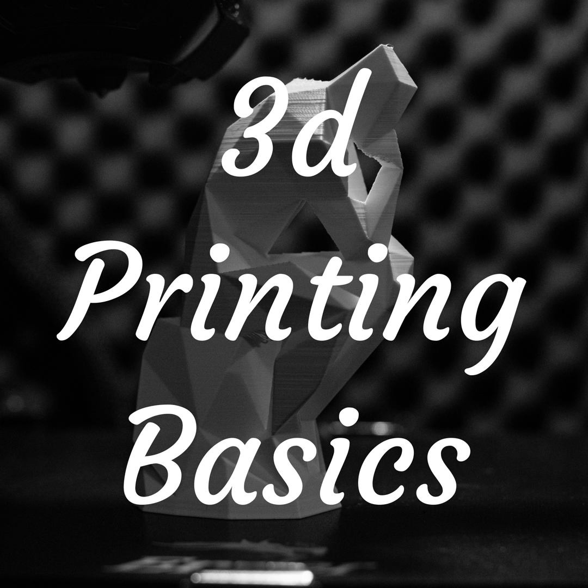Another thing that matters, and this is actually something that I didn't really know until recently. When I was previously trying to make really strong parts, I always just upped the infill. I would change it to 35, 40, 50, 60% if I needed to, and I always thought that that mattered more. But what I've learned recently and what I've been experimenting with is actually increasing the wall count. And what I've found and what other people have found, this is not just my opinion, this is a generally proven opinion, that walls matter more than infill.